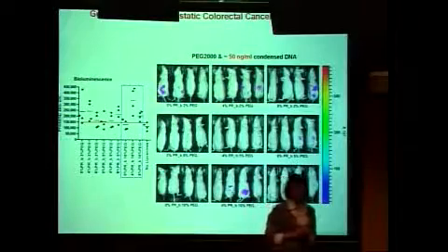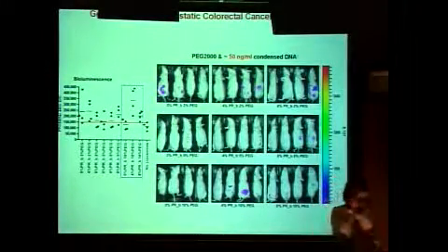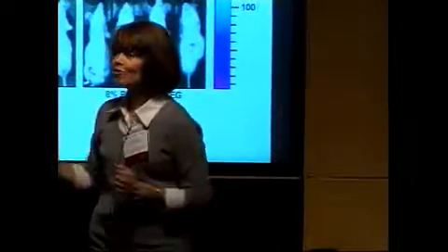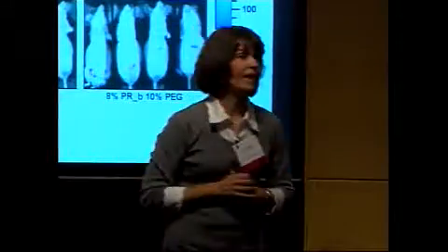The other thing that we realized is that we can do this job with a tiny amount of DNA, 50 nanograms per milliliter. What does that mean for you? When our collaborators are basically just injecting naked DNA to the mice, they use 25 micrograms per milliliter, and that's basically 1,000 times more. When we gave them the nanoparticles and we said, we prepared the formulations and they have only 50 nanograms, they started laughing. They said, there's no way you're going to get any signal, forget this. We said, yeah, we have the ground, we might as well try this. So for them, it was impressive that you can do such a job with a tiny amount of the drug.